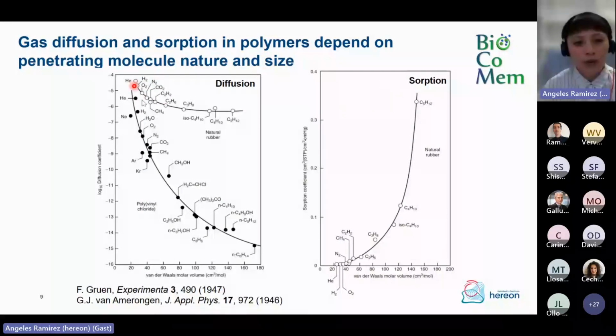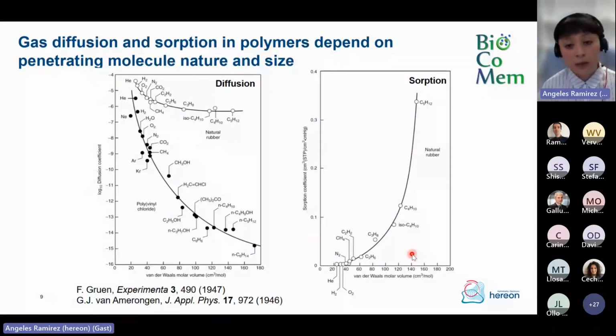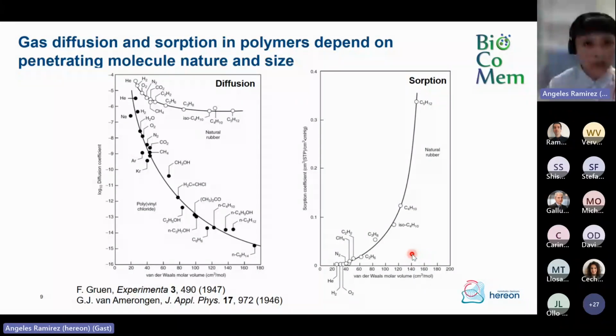Now, this is not the case for rubbery polymers, as we know that in this state, there is no restriction for the movement of the polymer chains. So the gases pass easily, so to speak, through the polymer. However, in the case of rubbery polymers, we will see that the solubility will play a major role, and this will determine the final permeability of a polymer. So, for example, in the case of the separation of carbon dioxide and nitrogen in flue gas treatment, as these are the two main components, it will be advised to use, for example, rubbery polymers, as the solubility of nitrogen and CO2 are quite different. So this will determine the required separation.